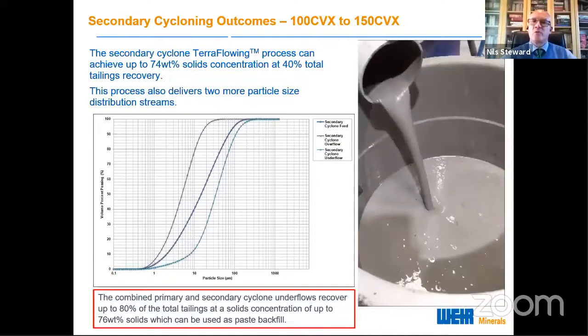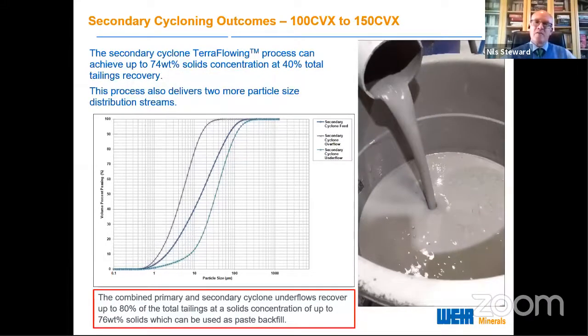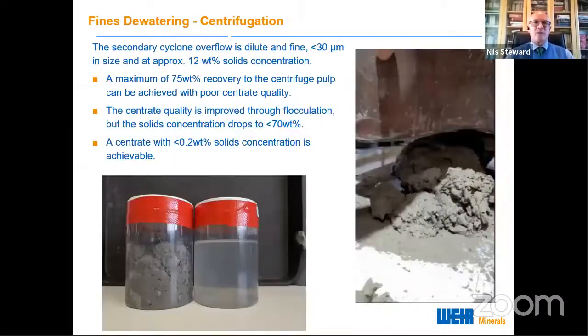So we're able to produce a paste backfill without a vacuum filter or vacuum filter belt in sight. Again, bear with me, I'm just having slides catching up here. We now have this very fine secondary cyclone overflow. It's dilute, there's a lot of water. We have a methodology of being able to pull out around 45 to 65% of the residual water before we put the product into the centrifuge.